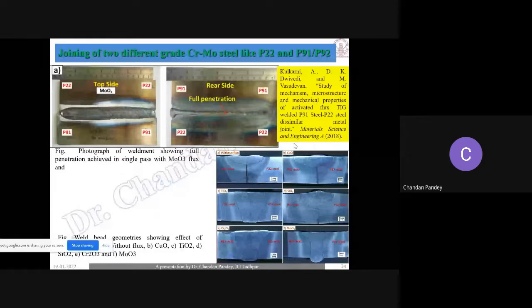In all these cases, we will get a small or narrow heat affected zone. But the problem is that with all these processes we can join plates of thickness only up to 10 mm. It is not possible to get penetration more than that. Here some research work has been published related to the activated TIG process for dissimilar joining, which is a more convenient way to get a joint of plate thickness up to 10 mm for different types of material. So what parameters do we consider in activated TIG? The main important parameters are welding current, voltage and other things. But the next thing we consider in the activated TIG process is the application of the flux.